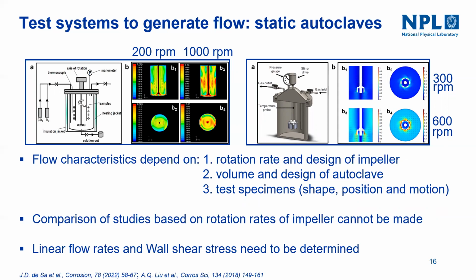So the majority of the studies have compared the corrosion of different studies based on the rotation rates. So this should not be done, because samples within the same autoclave system can have different flow conditions. So it can vary with the rotation rates and design of the impeller, the volume and design of the autoclave, and test specimens, the shape, position, motion. So this could be so many things. So the comparison of the studies just based on the rotation rates of the impeller cannot be made.